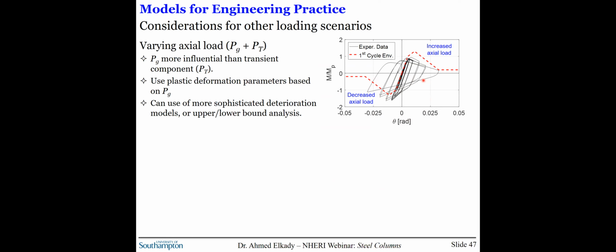Lastly, we also provided guidelines or considerations for other loading scenarios. What I talked about so far is all based on constant axial load. If you have a varying axial load, you can still use the modeling recommendations that I previously mentioned by looking only at the gravity load offset. Essentially you will get the same plastic deformation parameters, but in excursions where you have an increased axial load, you will be over predicting the strength. And in the opposite excursions, when the axial load decreases, you will be under predicting the strength. So an alternative would be to do an upper and lower bound type of analysis, or to use sophisticated material deterioration models that can capture these effects implicitly.